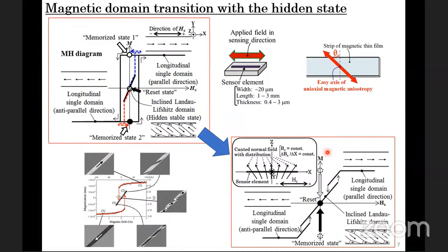The lower right schematic indicates it. The hidden state is able to appear in the case when a distributed normal field is applied. The inset of this schematic explains the distributed normal field, which is the surface normal field of the element substrate having a partial vector of in-plane field proportionally changing as a function of the longitudinal displacement.